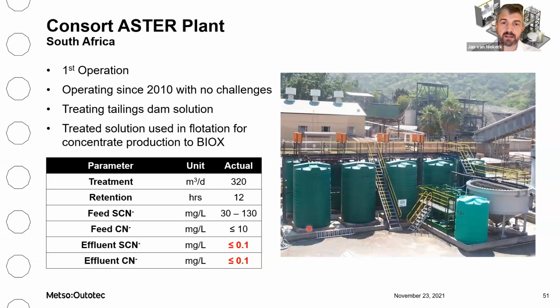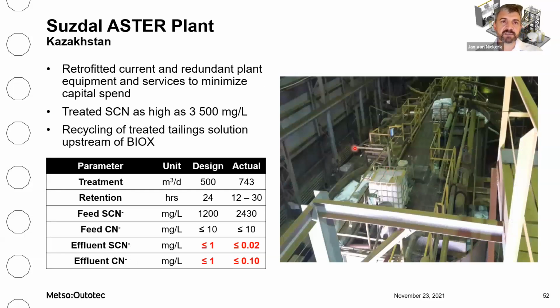These are just plastic water tanks, JoJo tanks, that are fitted with a sparge ring at the bottom, and overflow and feed pipes. And that is really the Aster process or Aster tanks for the Consort plant. The second installation was in the Suzdal Aster plant in Kazakhstan, and they retrofitted currently redundant tanks in the plant and repurposed them to be used as the Aster tanks. They have treated thiocyanate concentrations as high as 3,500 ppm. And again, the solution from the Aster is then recycled upstream of the BIOX.